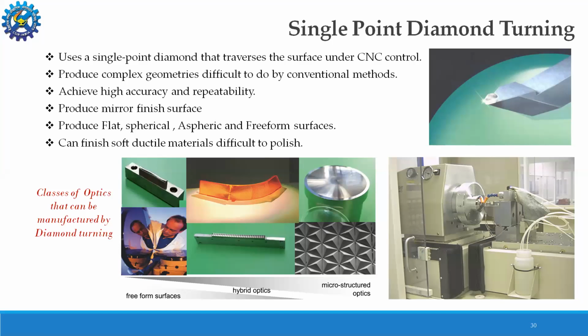and we can achieve very high accuracy as well as repeatability, and can produce mirror finish, that is, we are talking of surface quality of less than 10 nanometers, and we can produce any kinds of shape, whether it is a flat window, spherical, aspheric, freeform, or any kind of conic section or any freeform shape. And the disadvantage associated with grinding is that it cannot be used for soft as well as ductile materials. So single point diamond turning can finish soft ductile materials which are very difficult to polish.